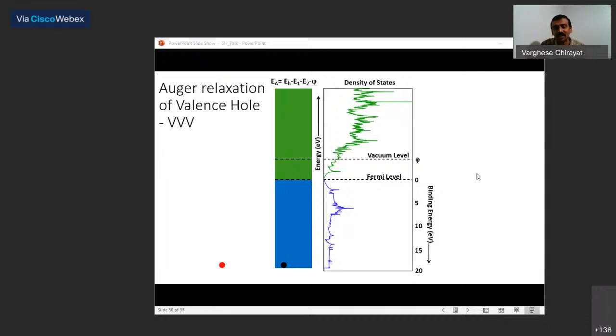Now let's see what happens. Now if a positron annihilates with this electron, which is deep inside this valence band of the graphene. The valence band of graphene is actually quite deep, which is quite unusual. It is 18 eV deep. Now this hole can be filled up by an electron from somewhere in the band itself, and that energy can be given to a second electron, and that electron can come out.